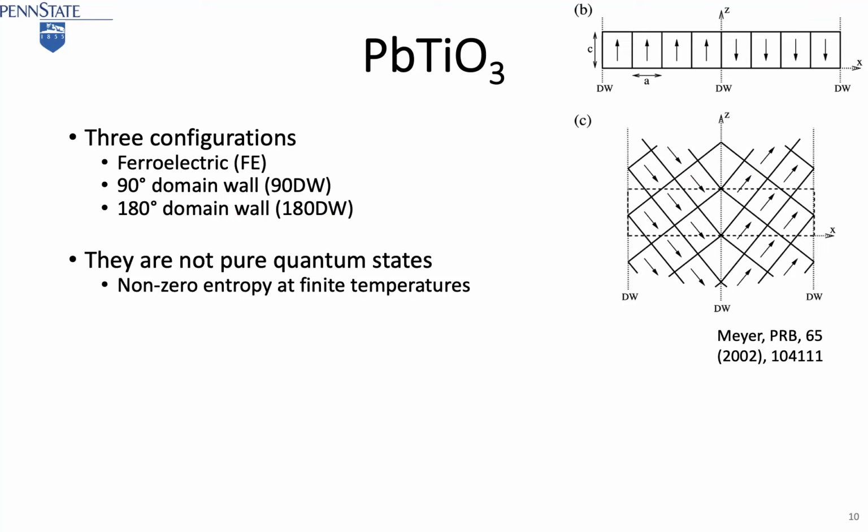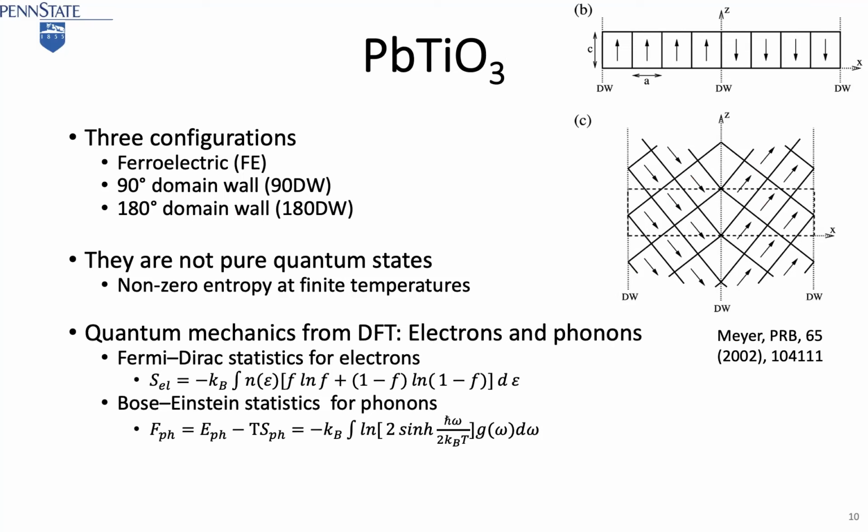So you cannot use statistical mechanics from the top down, put them together, but you can calculate the energy. How do you calculate it? You can calculate the phonons of them, right? You can do the electron contribution and the phonon contribution with the standard code. You can calculate them easily. It takes a few seconds, a few minutes maybe. And unfortunately, in this 2002 paper from Lanny's group, they calculated energy. They didn't calculate entropy. But the energy turned out not too bad in this case.